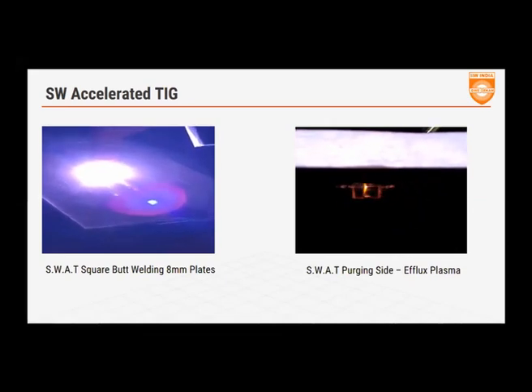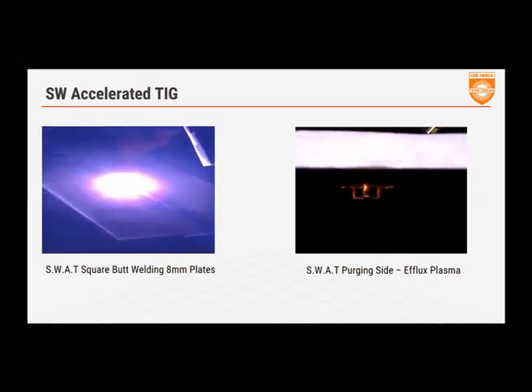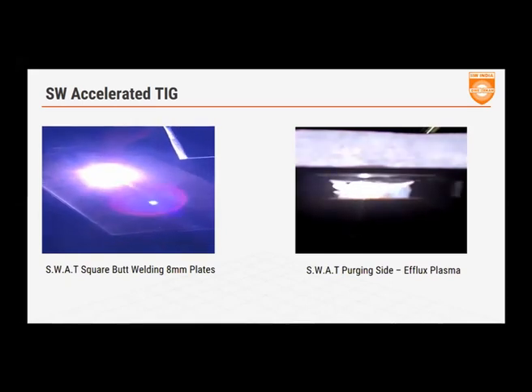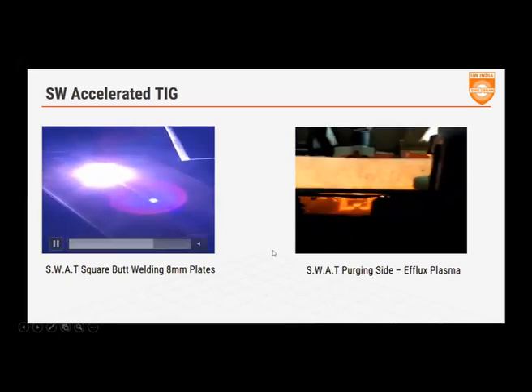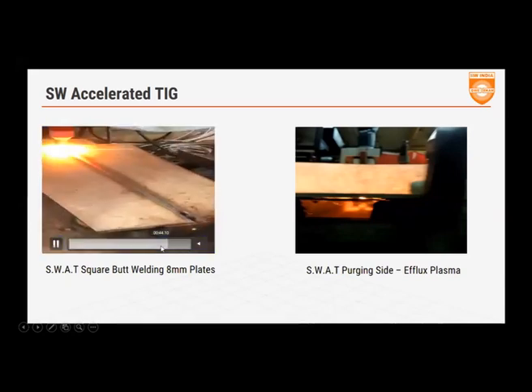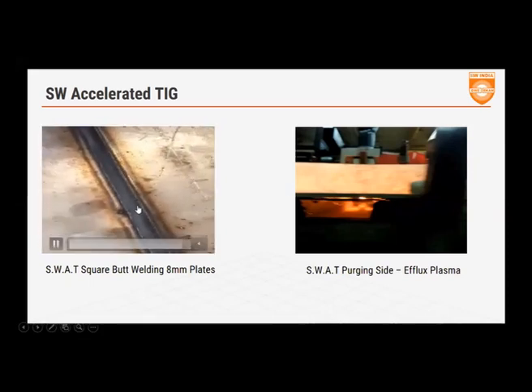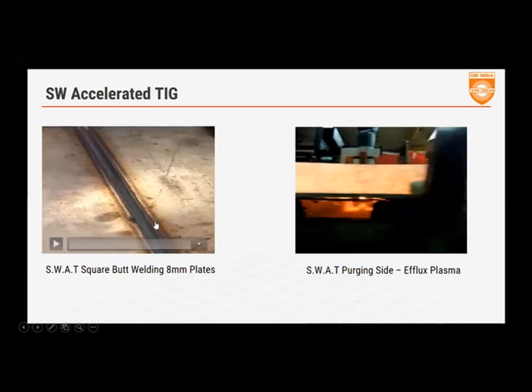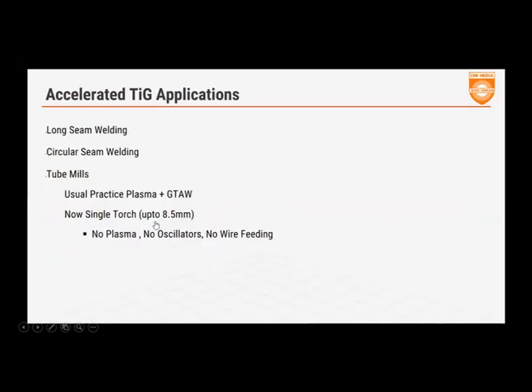And when you go into downslope, this is what happens. You're reducing current, your plasma is going off, your keyhole is shutting, and then you stop. If you see here, this 300 millimeter long plate took less than a minute to finish the welding. We welded at close to about 400 millimeters a minute. And this is the kind of weld joint you would get. No edge preparation, no undercuts, beautiful joint, no wire fed on it either. The applications can be wide. It can be used for long seam, circular seam, tube mills.